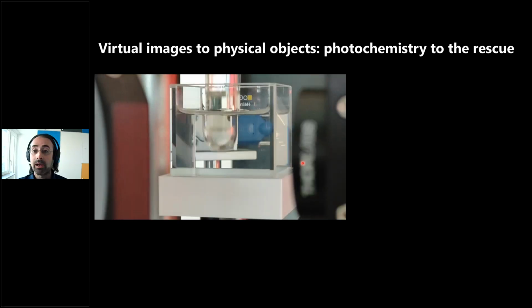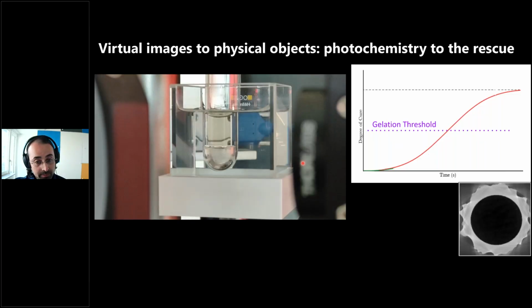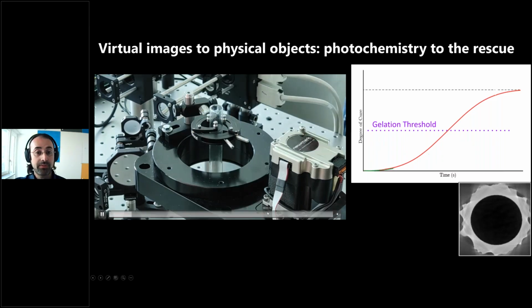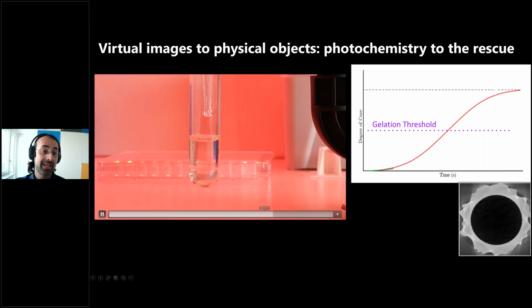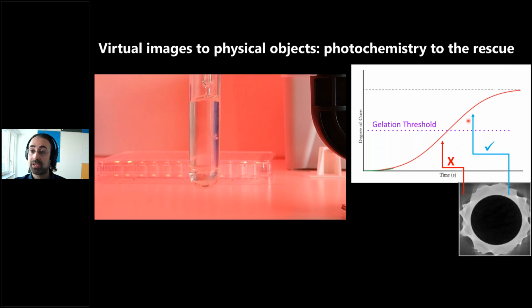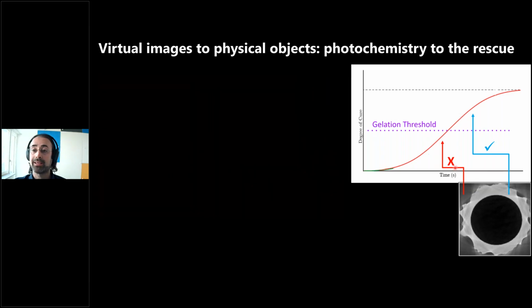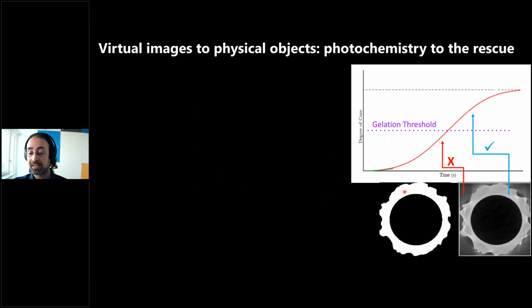Oh, apologies, I skipped a bit. After the object is formed, we can just wash with PBS and then retrieve our printed part. What is happening is that every part that we want to have crosslinked receives light just above the gelation threshold of the polymer, whereas every off-target area still receives light, but below the gelation threshold, so the polymer doesn't form a gel in that case. And in this way, you can essentially get a completely sharp reconstruction of the object you're trying to make.